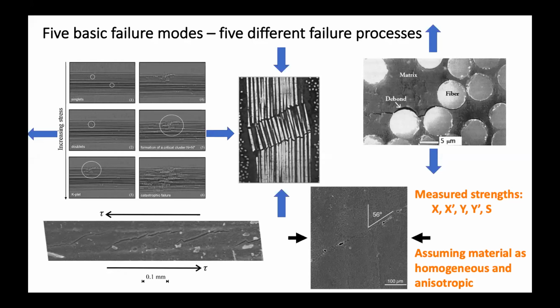But here in composite materials, each loading mode has its characteristic failure mode. Consider the tensile mode. It is highly statistical because it has to do with singlets and doublets and forming of a cluster of broken fibers. It is a highly stochastic process. Reverse the loading, and it's much more deterministic, much less stochastic. Failure is totally, of course, fibers have to fail, but they are failing in a very different way in the kink mode. You apply this loading mode, and Federico talked about the issues there. Those are the issues that only arise in this loading mode. It has nothing to do with any of the other 2.